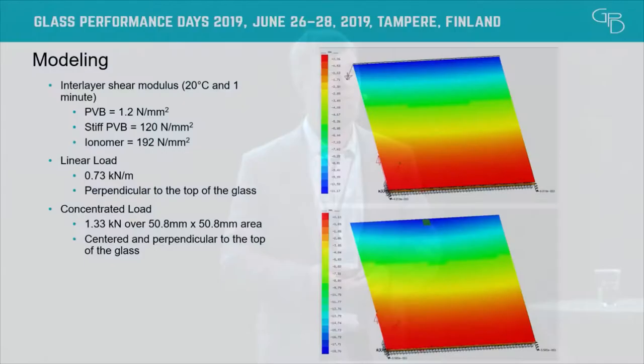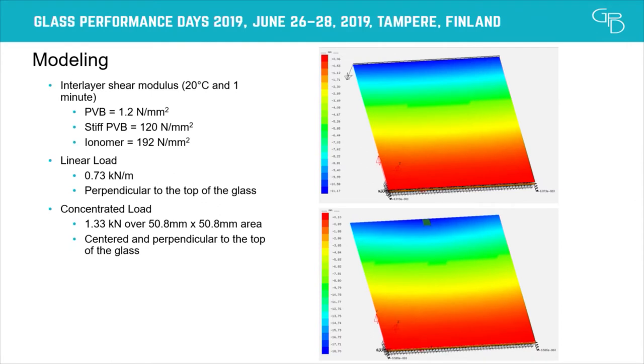For the interlayer shear modulus, I used our published values. For PVB it is 1.2 Newton per square millimeter, stiff PVB was 120, and ionomer was 192. So this was at 20 degrees C and 1 minute load duration. The linear load that was used was 0.73 kilonewtons per meter, and this was perpendicular to the top of the glass, pushing against the glass. And for the concentrated load, I used 1.33 kilonewtons.